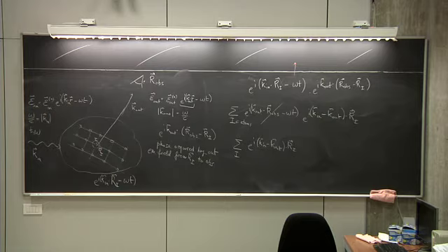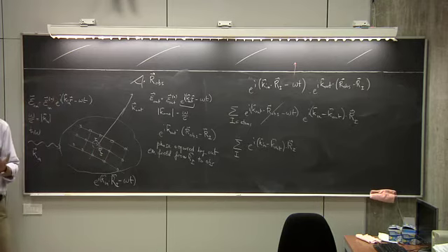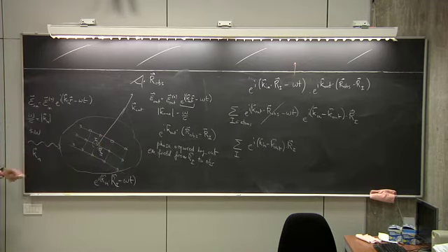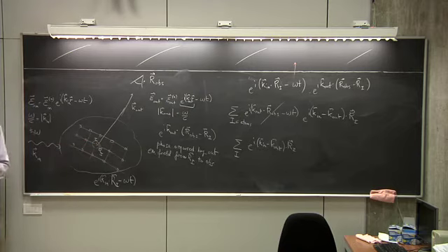Well, the theory is a bit more complex, and therefore I need to use this approximation, which is not really an approximation, because if you look at the charge density in a solid, it is primarily made of a superposition of atomic charges. You can, of course, describe it also in terms of free electrons in some cases, and we'll see examples of that. But we are not that far from the truth when we say that the electronic charge is primarily given by the sum of the atomic charges contributed by all the atoms. But you're right, this theory assumes that the atoms are all independent and the charge densities are independent.